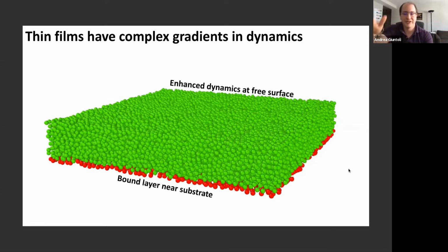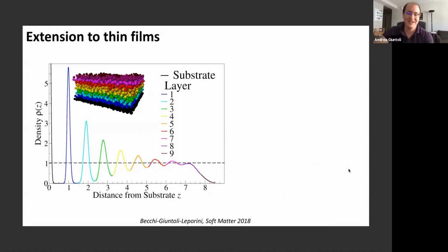You have a free surface with enhanced dynamics, and you have molecules that are stuck to the surface at the bottom. So you have these nice gradients in dynamics. And what I was trying to figure out was how to move all this modelization and this theory to thin films. And I failed more times than I care to share here, but in the end, we managed to have a good idea, which was to